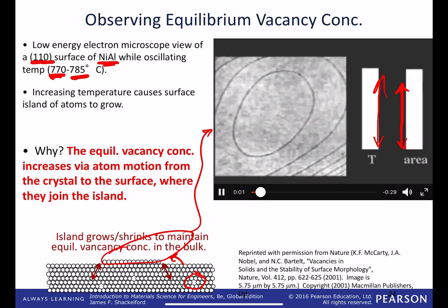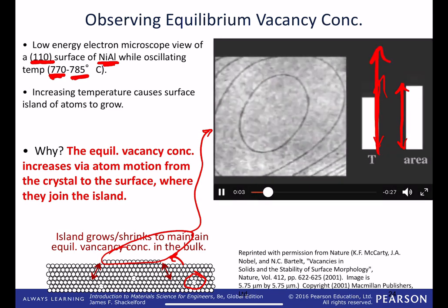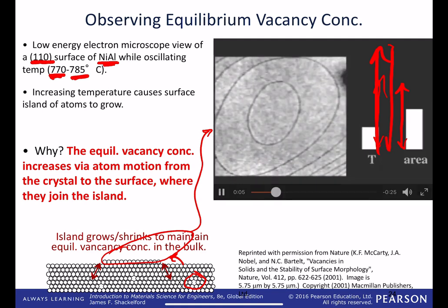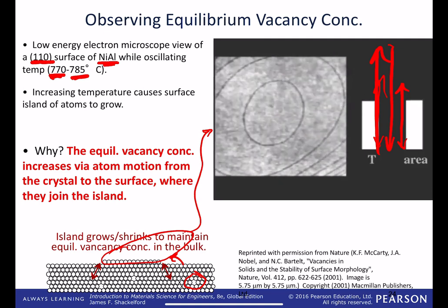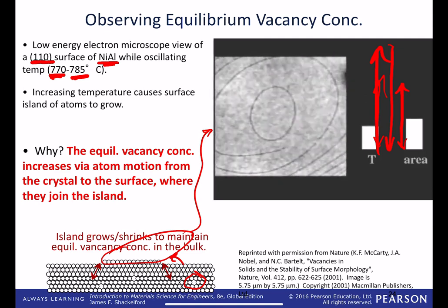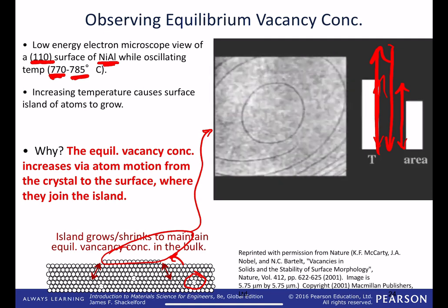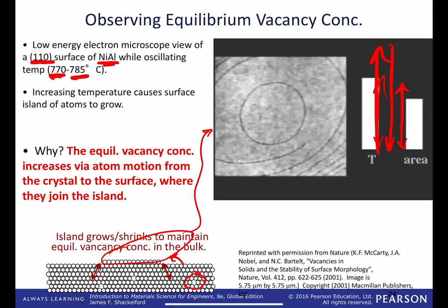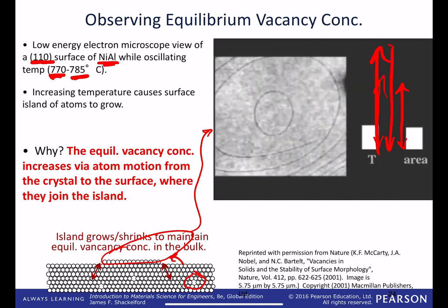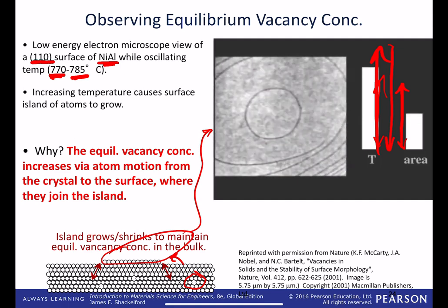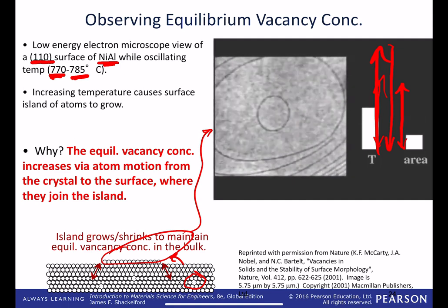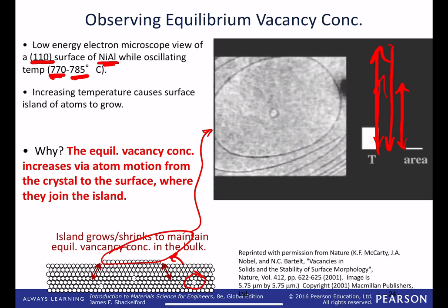Okay, so as we raise the temperature, the islands grow. As we shrink the temperature, decrease the temperature, the islands shrink. So vacancies are being created beneath the surface that we're watching with this microscopy video. And we're seeing atoms move to the surface as a consequence and growing an island of a (110) NiAl surface here. Really interesting result that puts to perspective the idea of calculating vacancies and what that means.